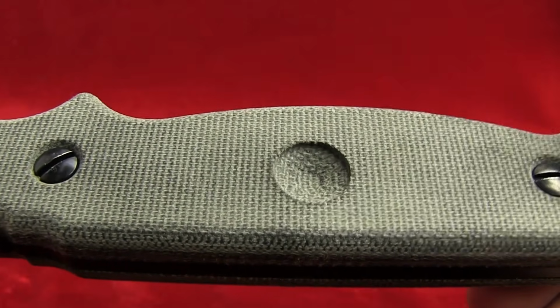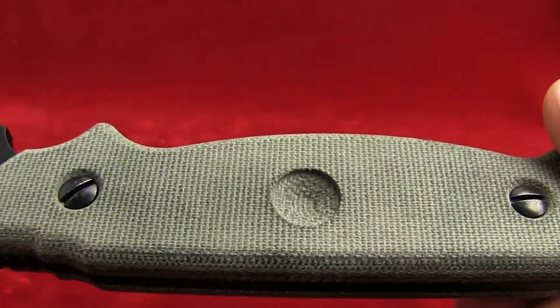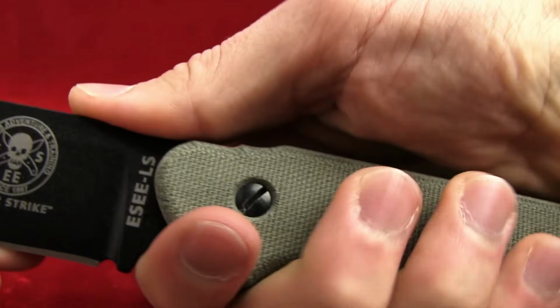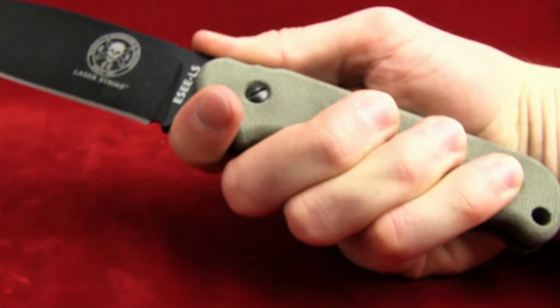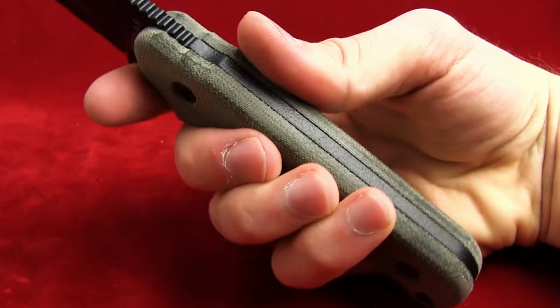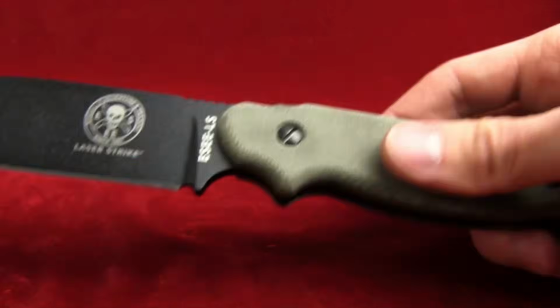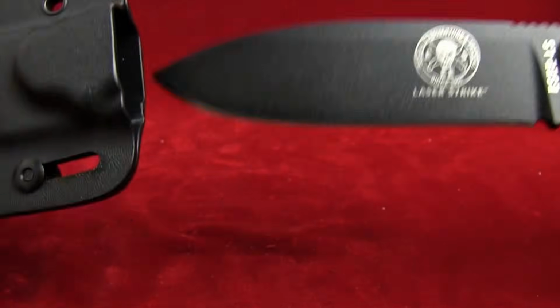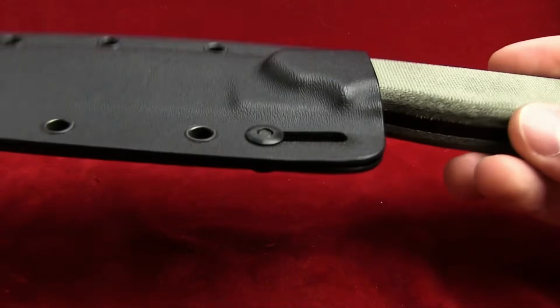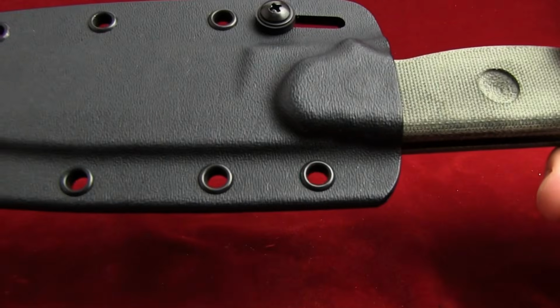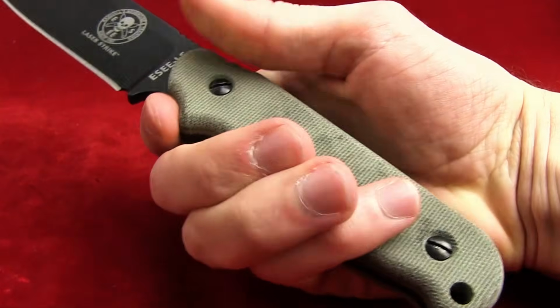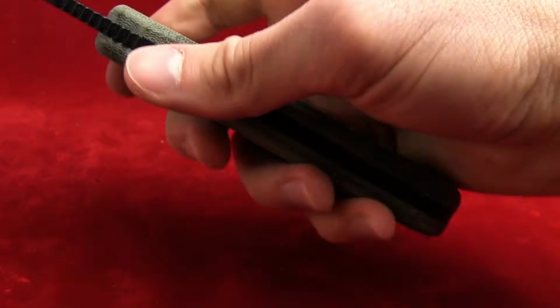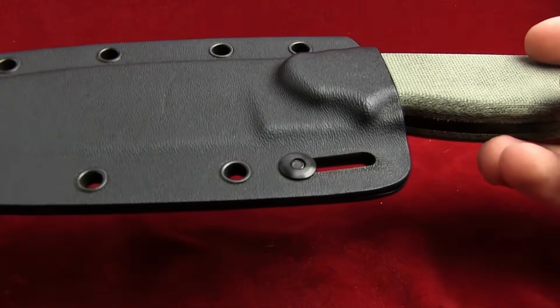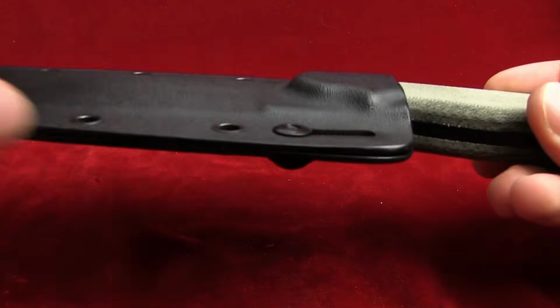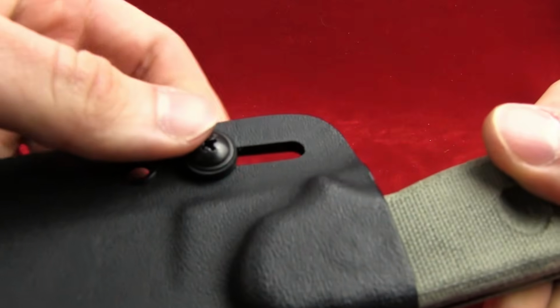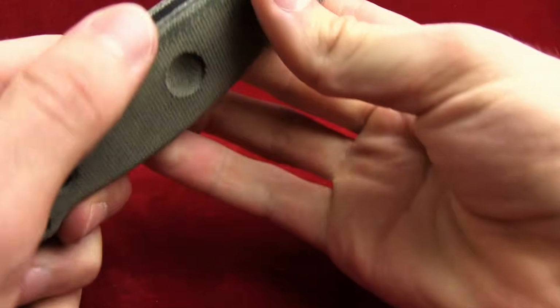In the destruction test, the Laser Strike battened through frozen knotted hardwood for 45 minutes without edge chipping. The same result the ESEE 5 produced in the previous destruction test, because 1095 at the right heat treatment genuinely does not chip under this level of abuse. The prying test produced no permanent deformation. The lateral stress test produced flex and return. The pommel, struck 40 times against tent stakes driven into clay soil, showed zero handle movement.